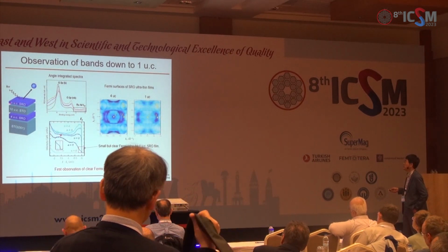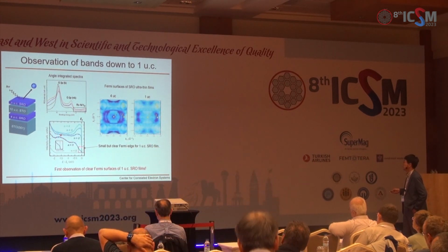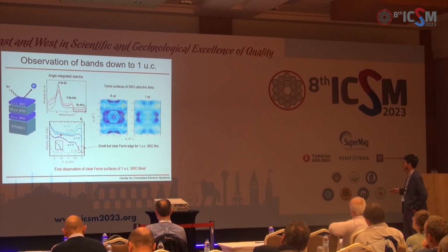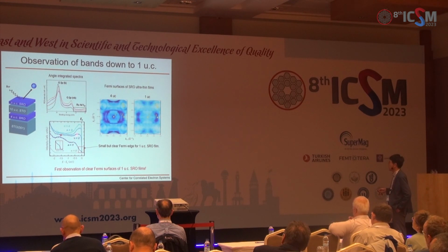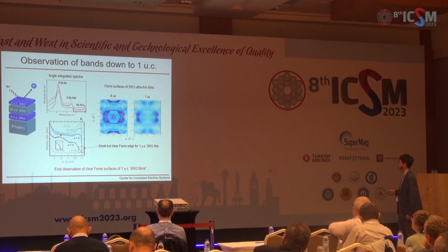Now I grow 1 unit cell, and I see some structure here. With 2 unit cells, 3 unit cells, and 4 unit cells, I have a very nice Fermi edge here. Now let's look at this thickness dependence. As we reduce the film thickness, this Fermi edge becomes smaller and smaller. At 1 unit cell it's almost 0, but we still have a finite edge here. It's small, but a very clear Fermi edge for the 1-unit-cell strontium ruthenate film.